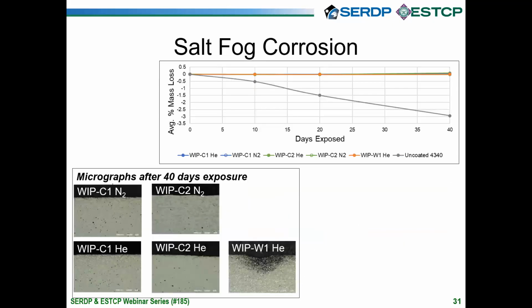We also evaluated corrosion, and on this slide I'm showing salt fog corrosion results. So in this test we exposed the cold spray samples to salt fog for 40 days. We also, for comparison, tested an uncoated 4340 substrate. What we found is that the mass loss of every coating was negligible compared to an uncoated 4340 substrate.